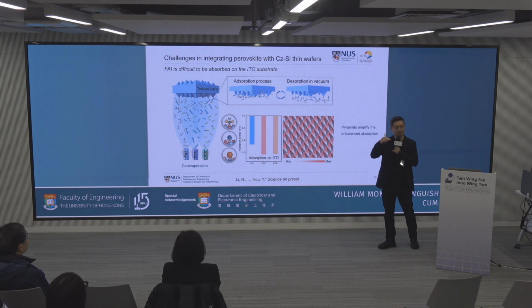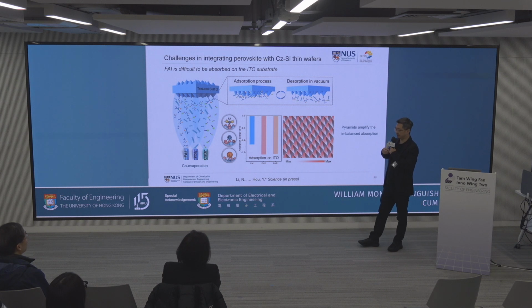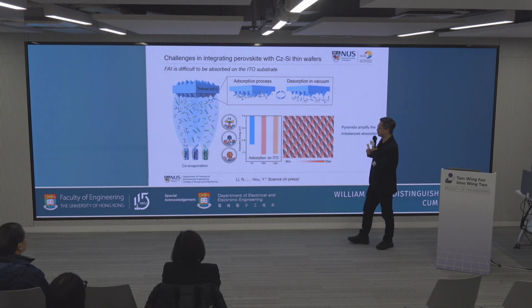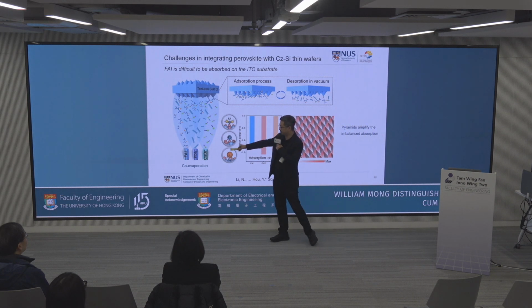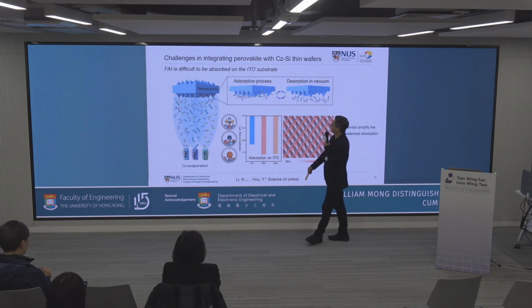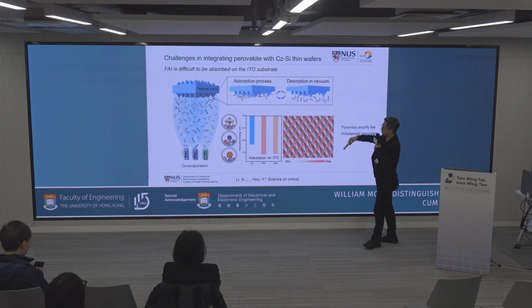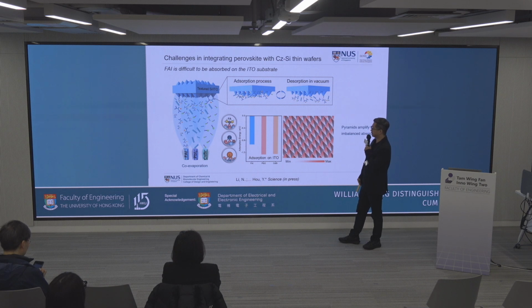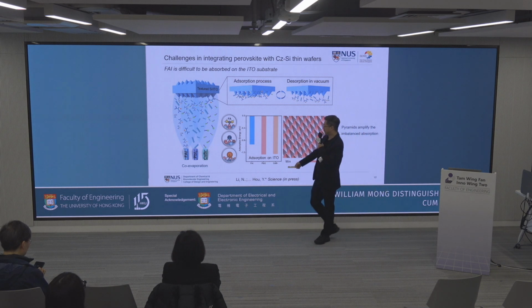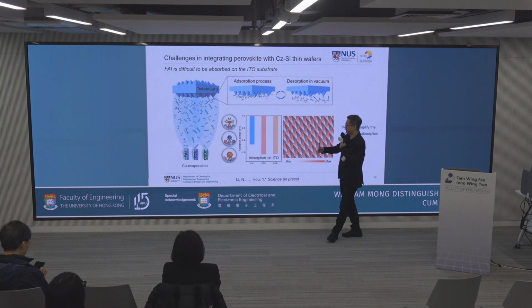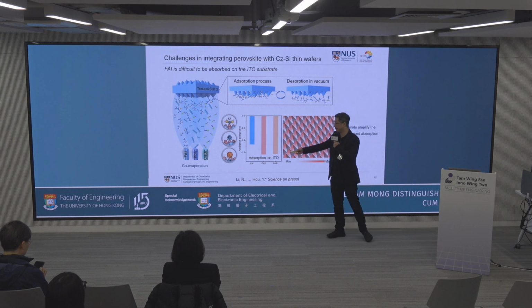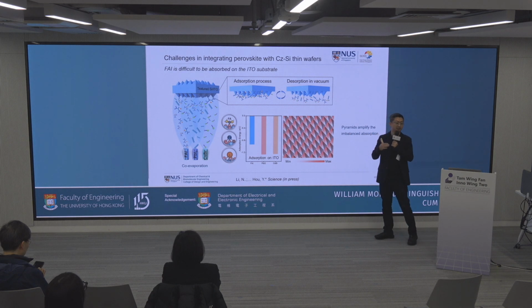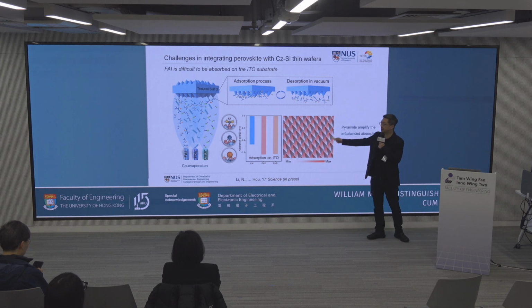to figure out how to deposit this perovskite on top of this very rough silicon, because silicon not only has this damage that causes roughness, but also the pyramid itself gives you this inhomogeneity of the deposition. And here you can see when we evaporate this, we use three sources: FAI, lead iodide, and cesium bromide, and actually they have a different absorption energy of each component on this substrate. What we realize is, this organic component, FAI, is less easy to absorb on the substrate, and the inorganic one is easier. So it creates this imbalance of the absorption on the substrate. And this geometry of the pyramids makes it even worse.